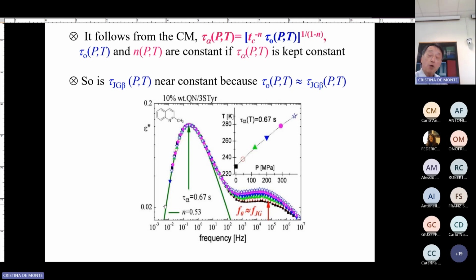So in other words, the coupling model predicts this behavior of the JG relaxation, which is realized in experiment. So this is theory which does that, but because of this relation here, is because we found these partners, the primitive and the JG are partners. So everything is verified nicely here in this experiment.